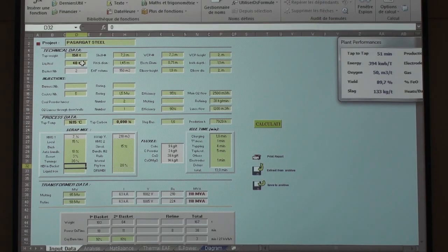if you increase the hot heel, you slow down the furnace. The hot heel is necessary to have an aggressive power profile. Because if you don't have hot heel, then you bore down and, as the electrodes are in the scrap and the roof is protected, you go full power. But then you go down to the bottom, and if there is no hot heel on the bottom, then you dig out the refractory. So the hot heel is there to maintain a certain buffer to absorb the energy of the high power furnace.